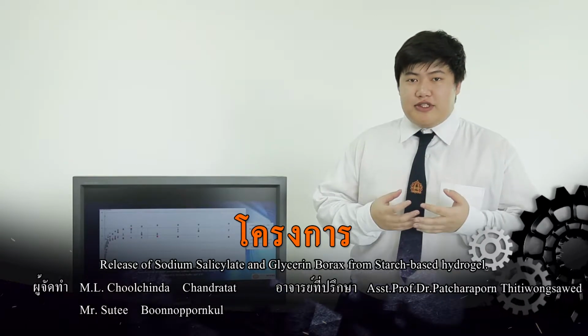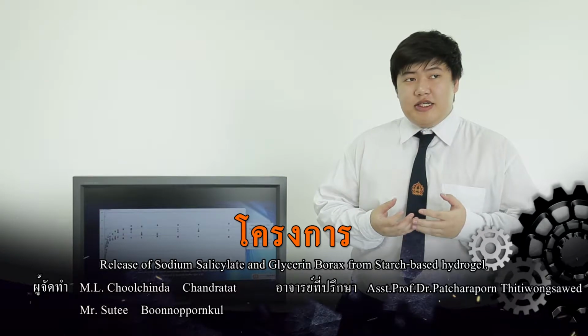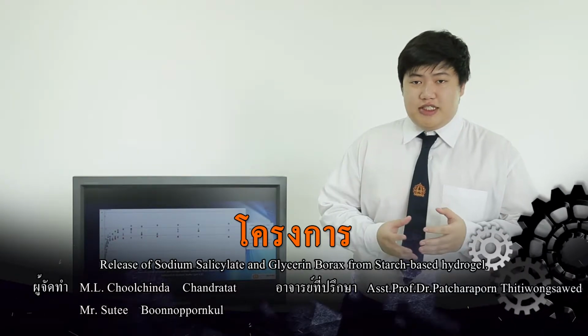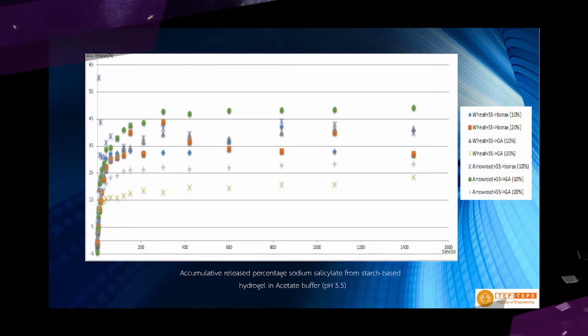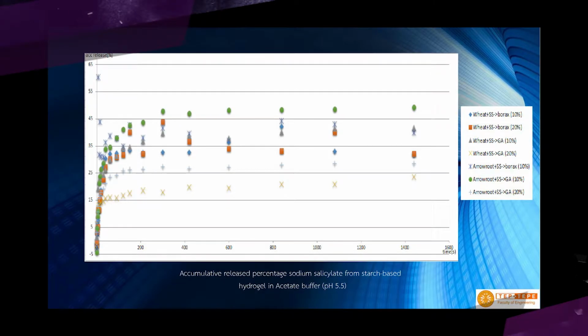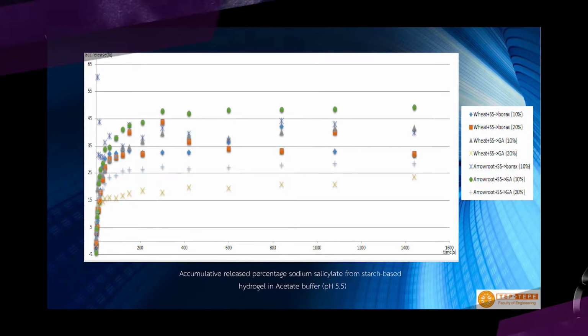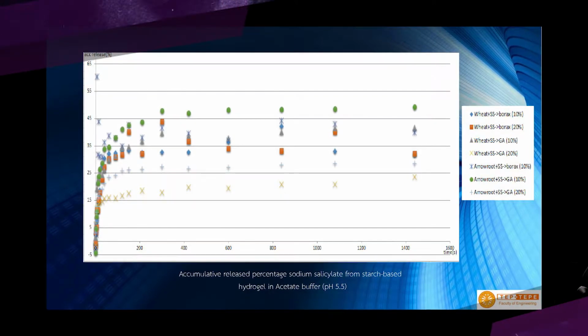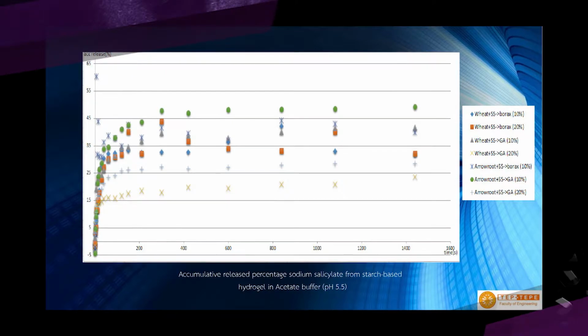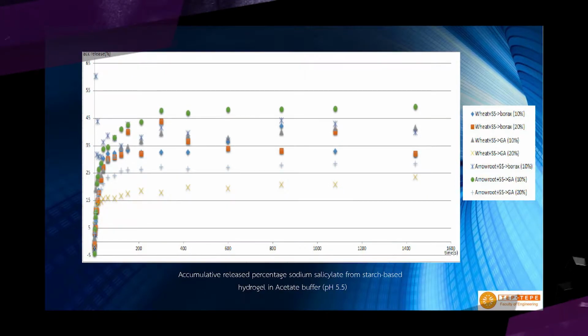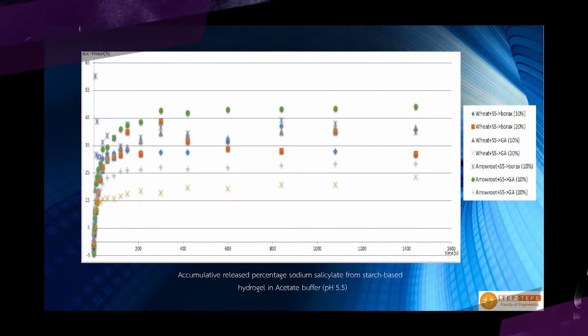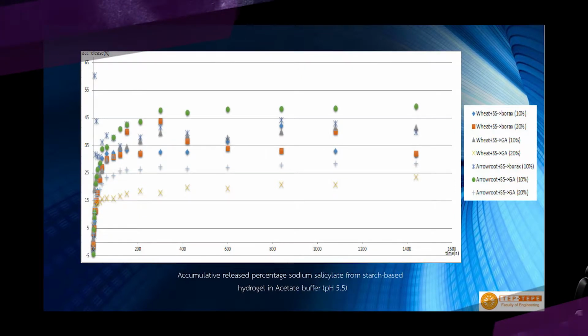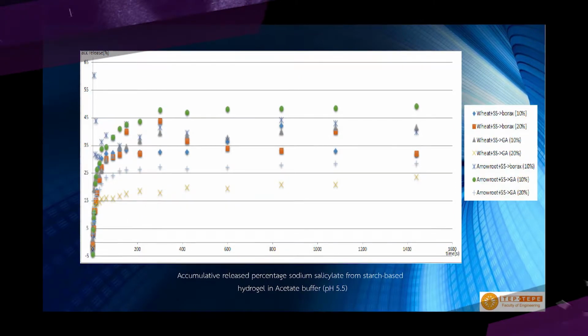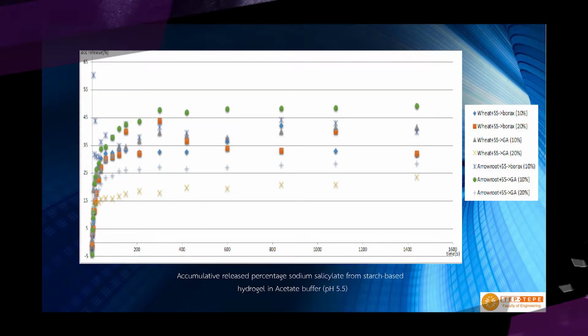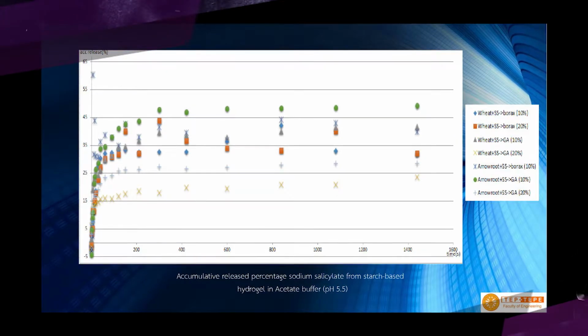Today we are going to present our project, release of sodium salicylate from starch-based hydrogel. The hydrogel we synthesize starts with wheat or arrowroot starch, and then we mix with a cross-linking agent, borax or glutaraldehyde, or we first mix with the drug, sodium salicylate. Then we synthesize to form the drug-loaded hydrogel, and then we study the release kinetics of the starch-based hydrogel and the absorbency of the hydrogel.